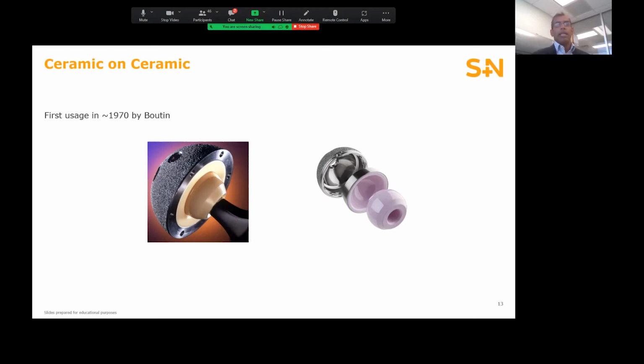In approximately 1970, ceramic on ceramic bearings were utilized for the first time. Ceramics are attractive because they have the potential to have very low wear. They have really high hardness, are very abrasion resistant, and have improved wettability over metal, so they are wettable. However, some early ceramic on ceramic devices exhibited incidences of fracture and loosening.